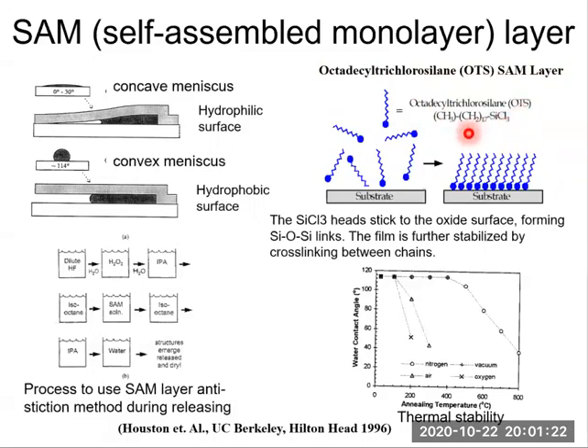The OTS molecule has a trichlorosilane head. Its head is silicon Cl3, trichlorosilane, three chlorines. The trichlorosilane heads stick to the oxide surface, forming silicon-oxygen-silicon links. And the film is further stabilized by cross-linking between chains. We know that OTS has an 18-carbon-long alkyl chain. So this tail is an 18-carbon-long alkyl chain.